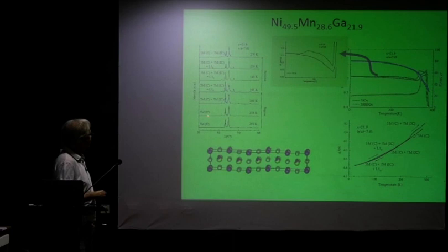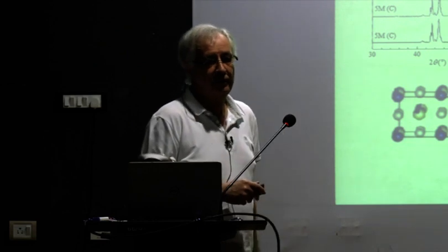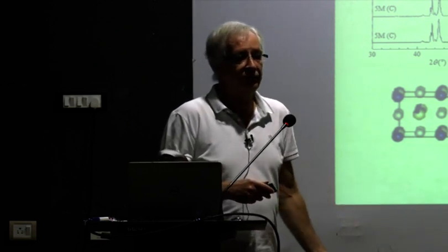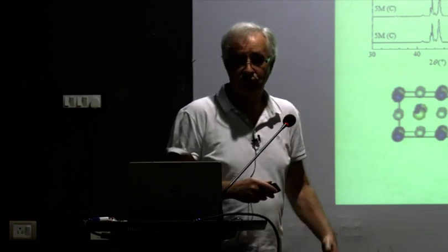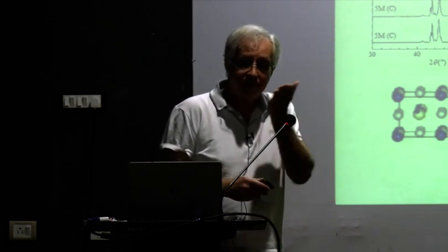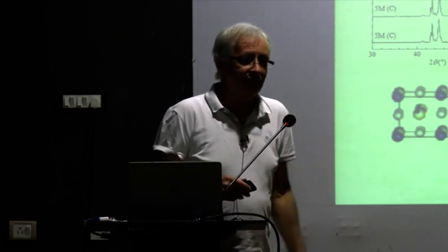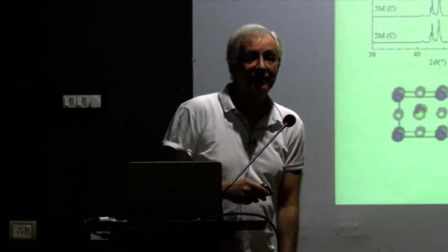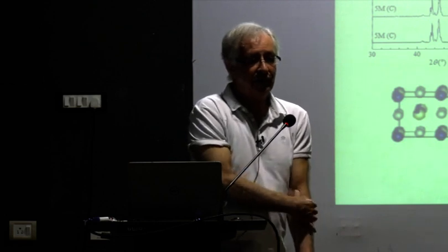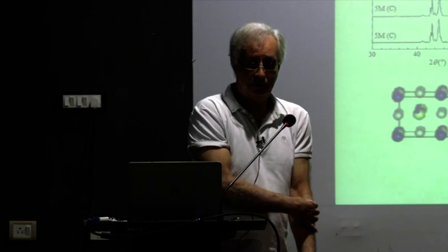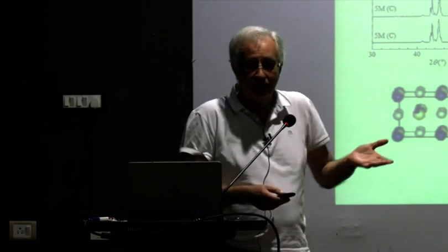It remains as a commensurate 5M state. Now, why do we say commensurate? Because the analysis tells us that our Q vector is in the order of about 0.4. There's no other reason. It can be 0.405, it can be 0.406, it can be 0.4, exactly. So this business of modulation, or the incommensuracy, is something more general rather than being the exception. So when you have a Q equal to 0.4 and a 5M commensurate modulated state, that is just a number, and that is a special case of the incommensurate condition.